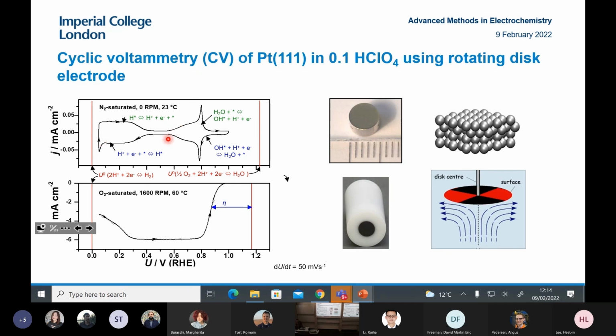So what happens is, as you cycle the potential down, you start to see hydrogen being adsorbed, you get negative currents, and then it gets oxidized off. And when you go to more positive potentials, you get OH being adsorbed and then it desorbs. At least on platinum 111, you can see it's completely symmetrical. That means hydrogen adsorbs at the same potential as it desorbs, so it's at thermodynamic equilibrium.